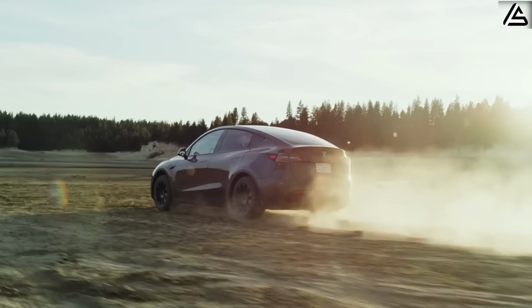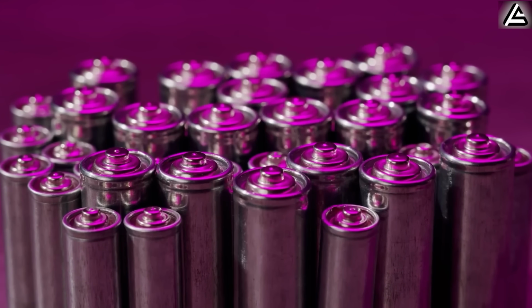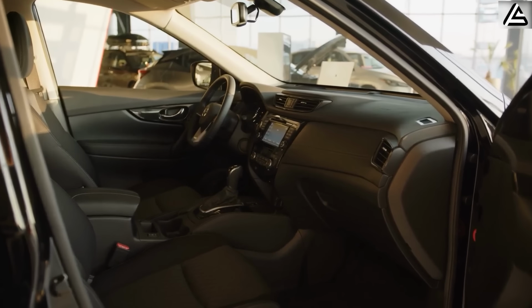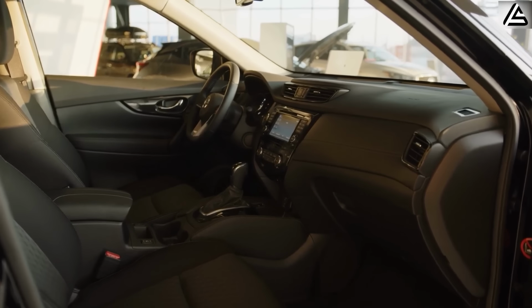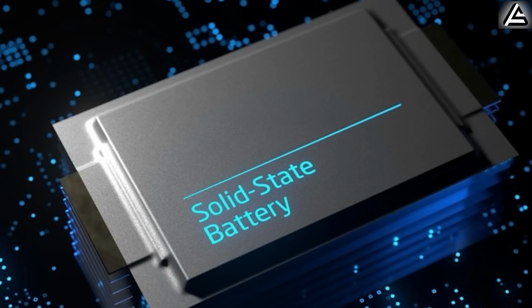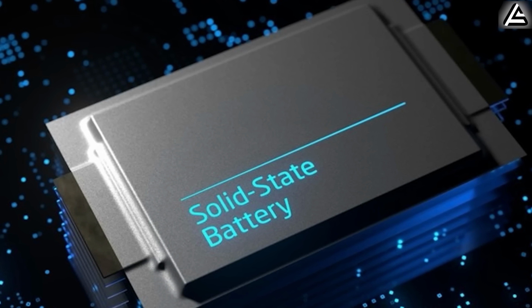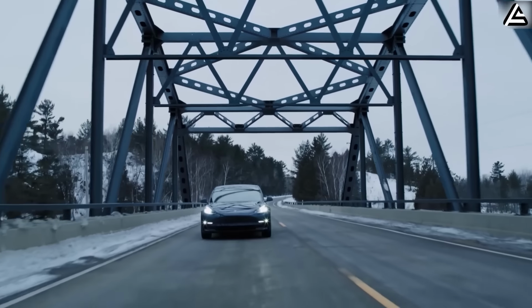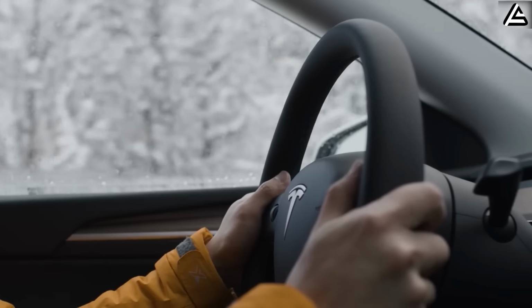Take a Model Y in extreme winter conditions, for example. With a traditional lithium-ion battery, warming up the cabin from negative 20 degrees Celsius to 20 degrees Celsius can take 15 to 20 minutes, and a significant portion of the battery's power is wasted in the process. But with the solid-state battery's 95% heating efficiency, the same process takes only 6 to 8 minutes, which shows a 60% reduction in heating time.